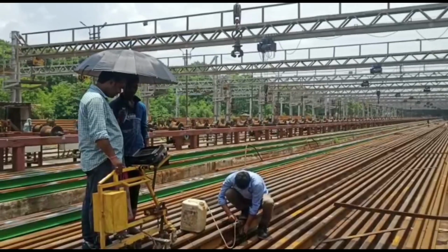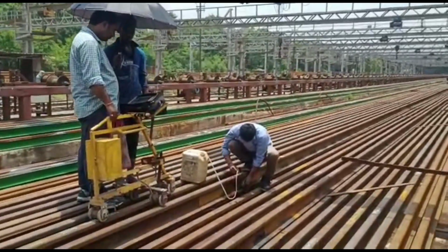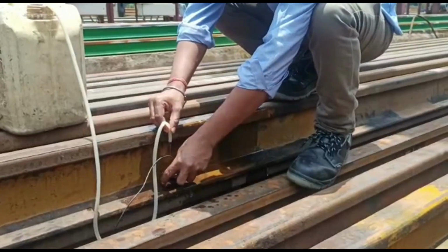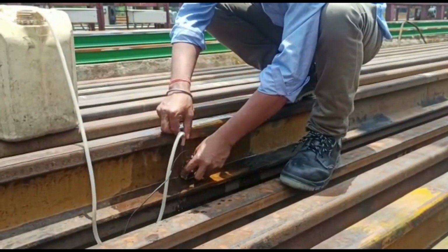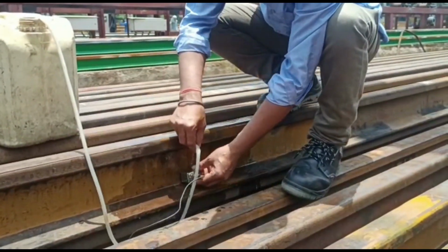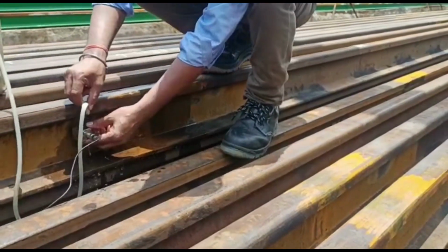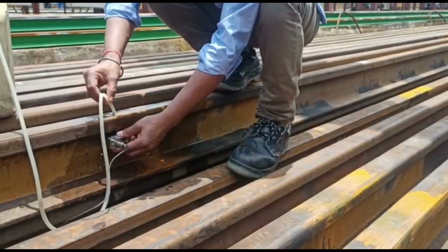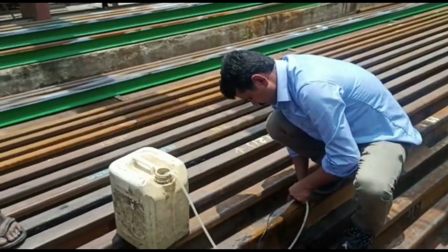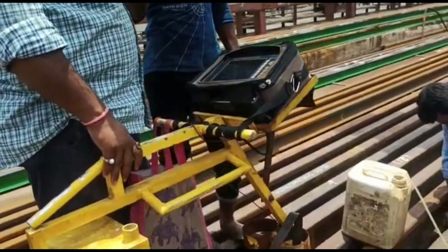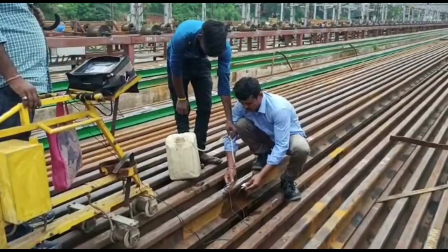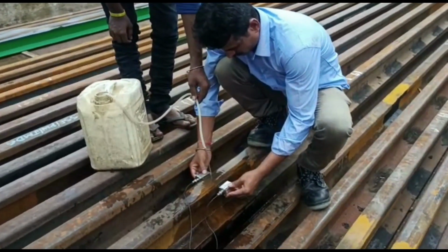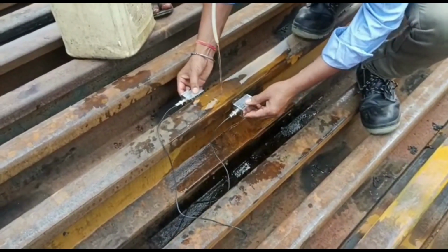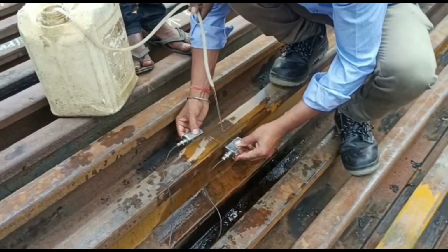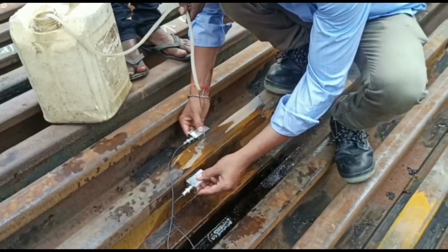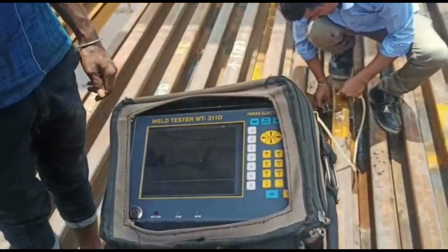All welds shall be subjected to ultrasonic testing for detecting the presence of internal defects in the rail weld. So the complete rail shall be scanned. How is it scanned? The complete flange portion, web portion and head portion with 70-degree probe and 45-degree probes. With the 70-degree probe, the flange and web portion, then two 45-degree probes in the head portion, are completely scanned. If any internal defect is there, it will be shown on the machine screen.